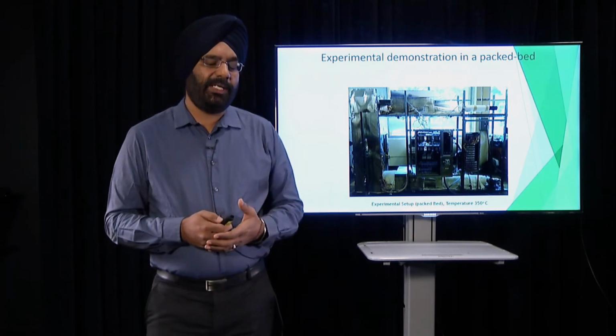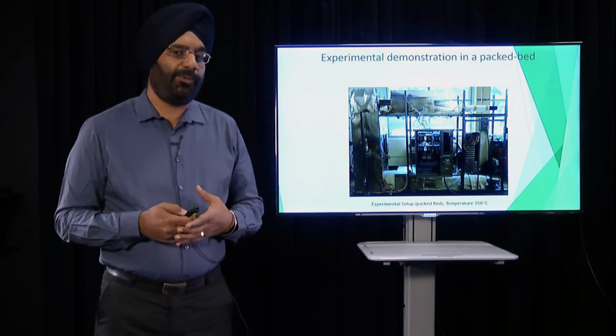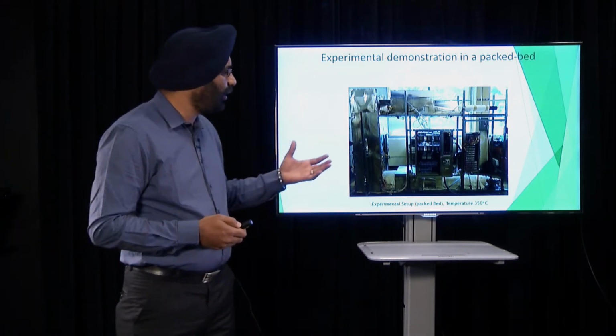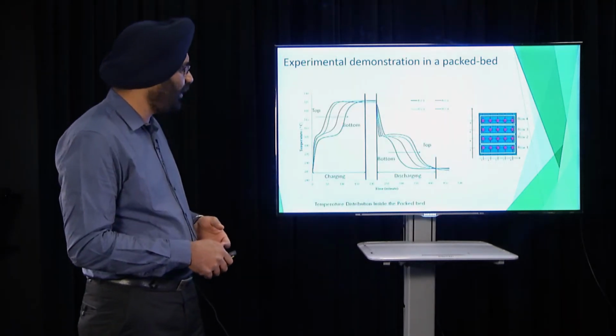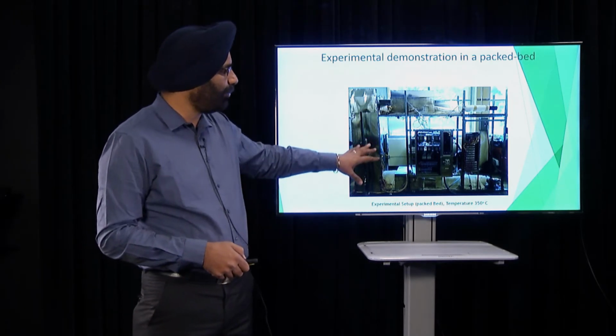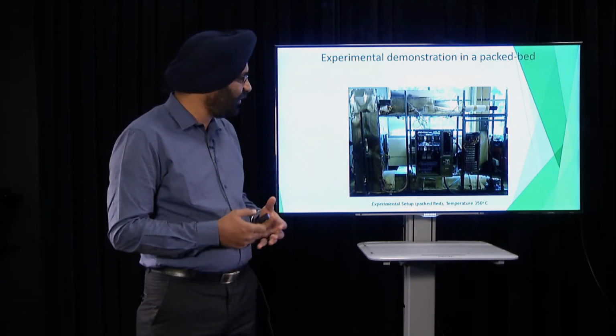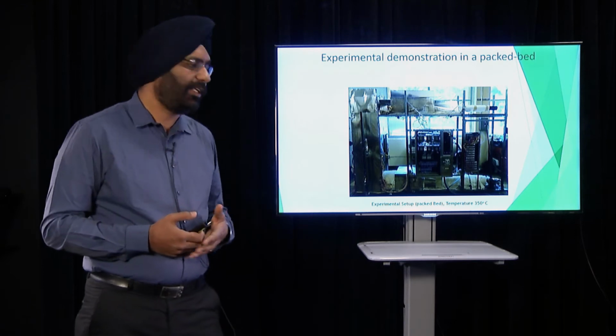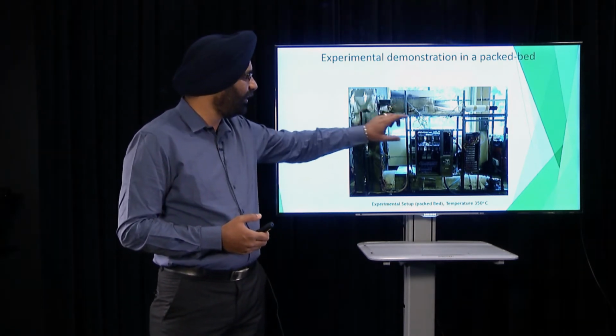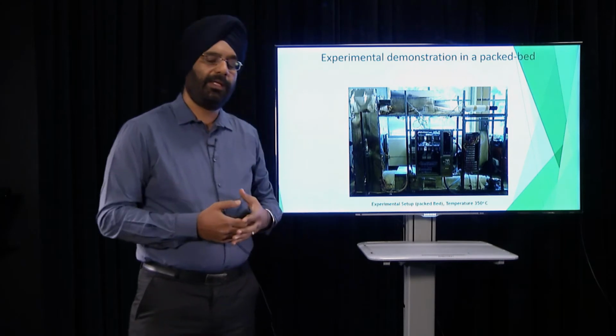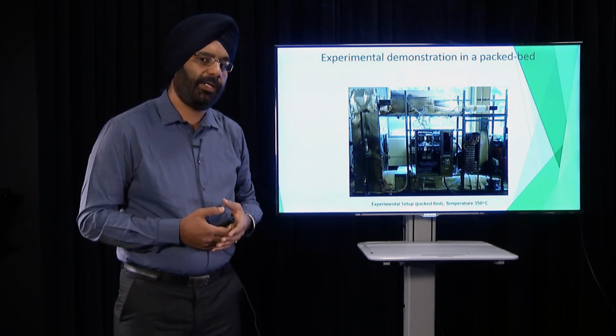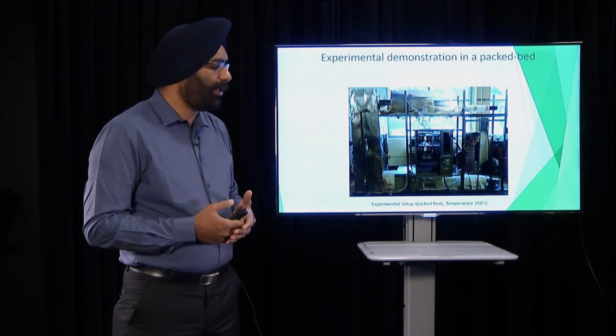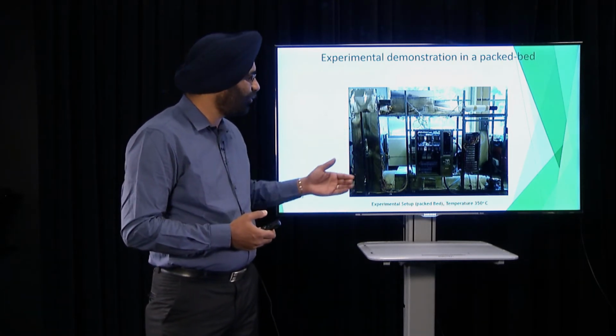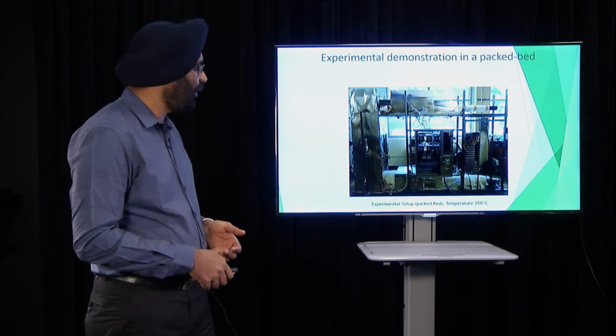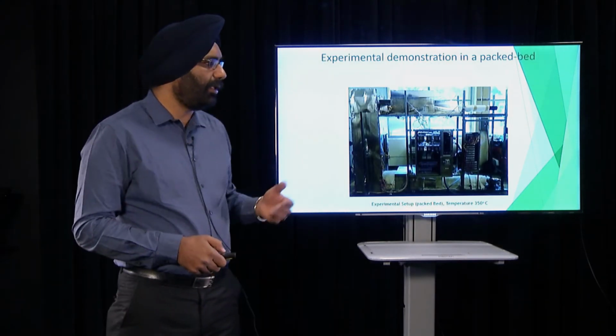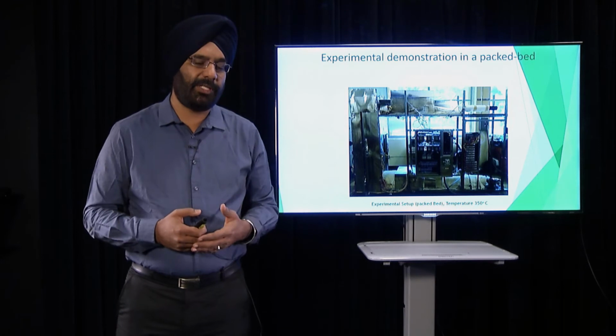The test which we did initially was on an individual scale, but then we wanted to test it on a large scale in a storage tank. So this system is built in the lab, and this is a large storage tank, perfectly insulated. You are seeing these sheets and also insulating material in there. They are perfectly insulated so that there is not much thermal loss. And inside the storage tank there are a number of capsules, more than 1,000 or so.